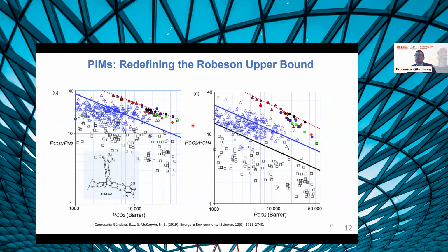As I mentioned earlier, because of this porosity, these PIM polymers give very high permeability, so they have redefined the Robeson upper bound for the last 20 years. So this was the 2019 upper bound. You can see that these PIM polymers give really high gas permeability and also reasonable selectivity. So one of the challenges is that the permeability and selectivity are not enough for industrial applications.